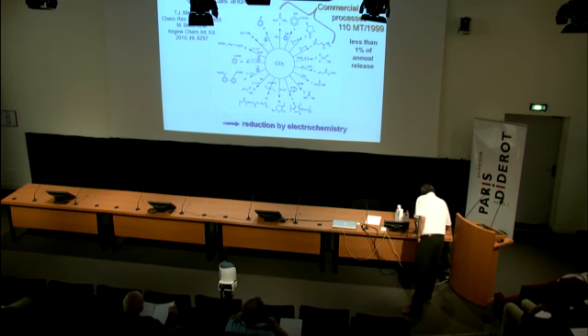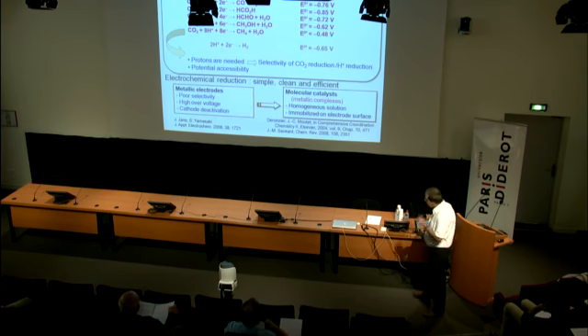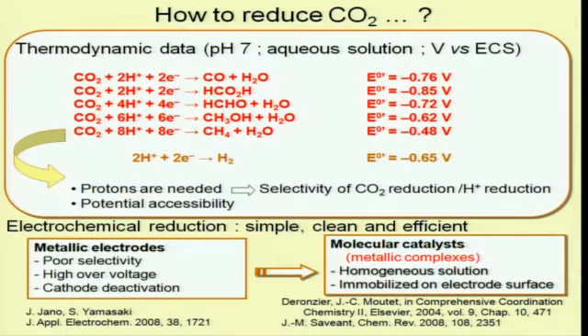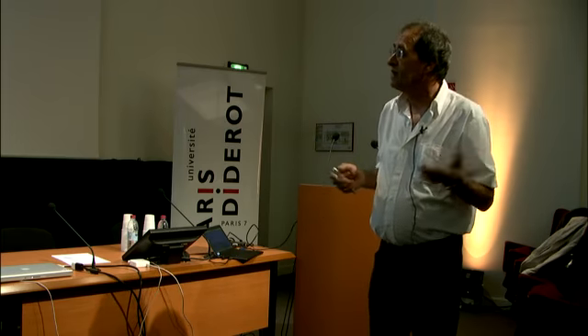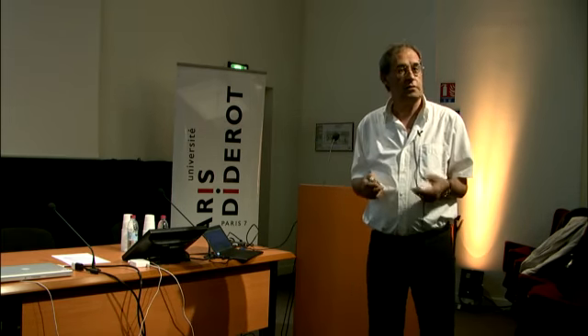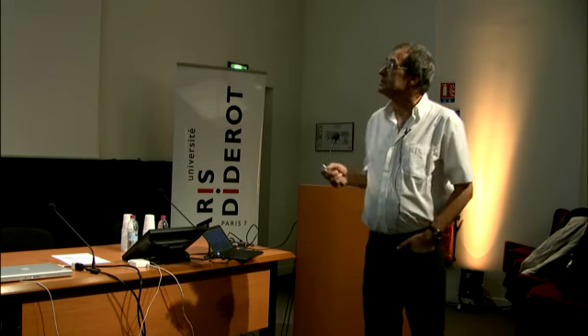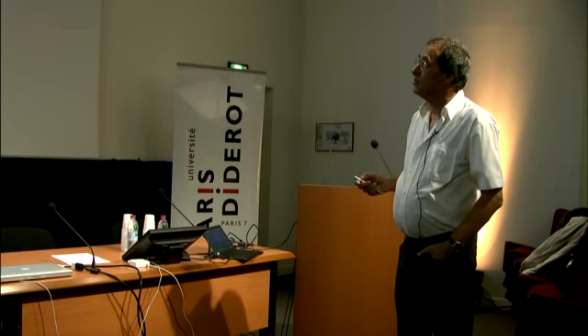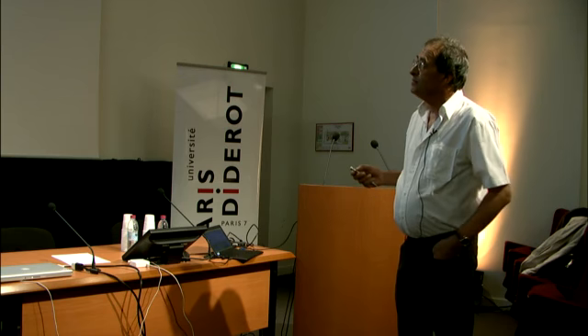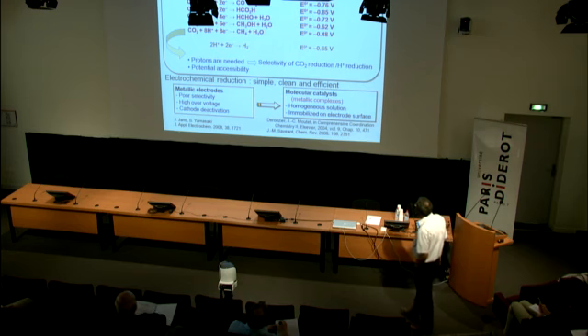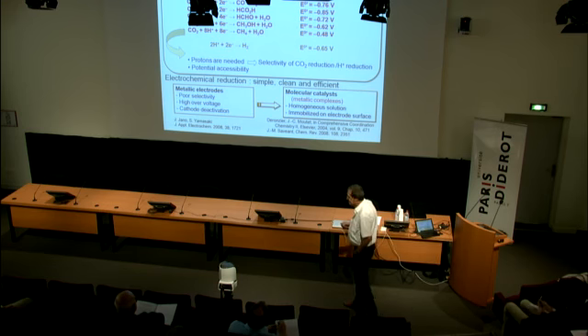The problem is that if you have any chance to make this into an industrial process, it's necessary to use very simple conditions. I mean, pure aqueous solution as electrolyte, for instance, and very usual electrodes. So how to reduce CO2? That's the thermodynamical data at pH 7 in aqueous solution, potential versus SCE.